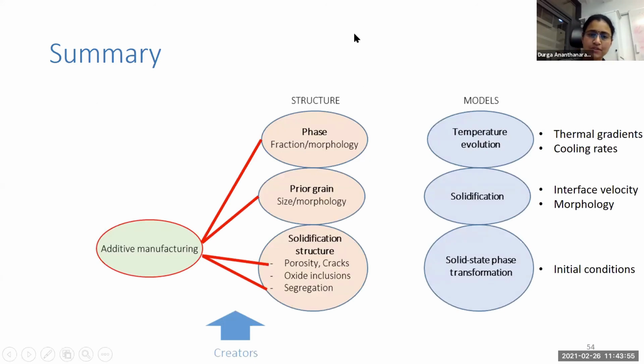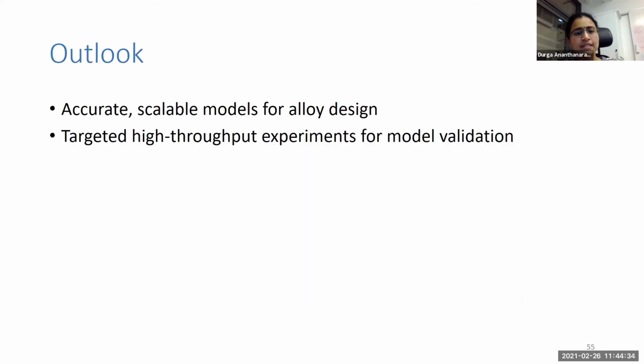So we looked at four different aspects of the process structure correlation: the phase formation, morphology, the grain structure, crack susceptibility, and segregation. To do this, we looked at different models. We saw from the temperature evolution that thermal gradients and cooling rates are key inputs for other models. From the solidification models, we saw that the interface velocity and the morphology are key if we want to predict things like phase formation. And for solid state phase transformation, we saw the importance of using the right initial conditions if we want to predict them correctly.